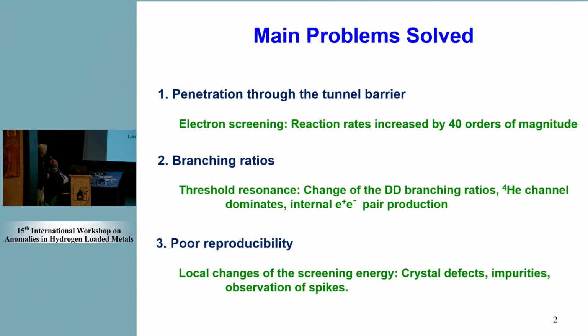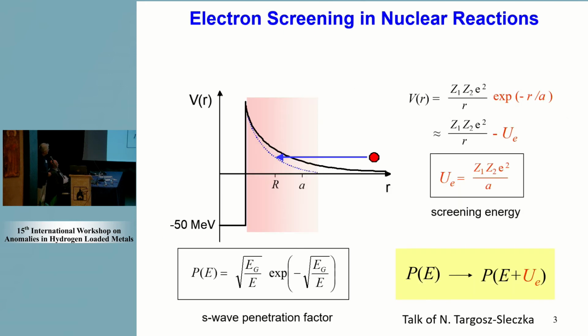And then the third point is the poor reproducibility, because even small impurities, changes in the lattice, defects in the lattice can completely change the screening effect and then the final reaction rates at thermal energies. Okay, so how can we do it? First one, and this will be talked about by Natalia Targosz-Lęczka in the next talk.